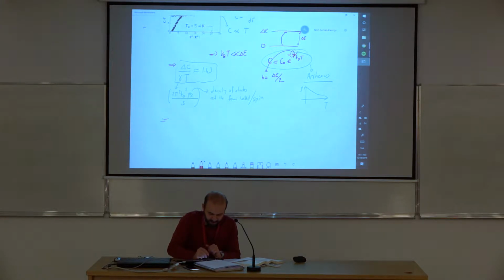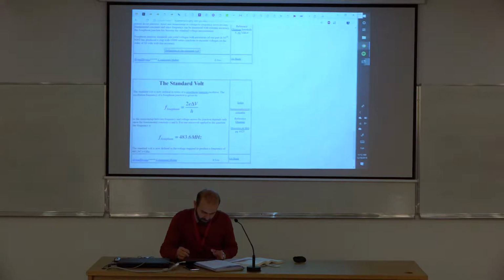Then another success is that after some lengthy algebra, what you need to do is actually solve the Schrödinger equation for two electrons as well as their interaction with the crystal. And once you do this, you can write down the findings of the BCS theory. One of the other findings is that this energy gap follows such a relation. So delta E divided by kB Tc, this is the critical temperature for the superconducting transition, is equal to 1.76.